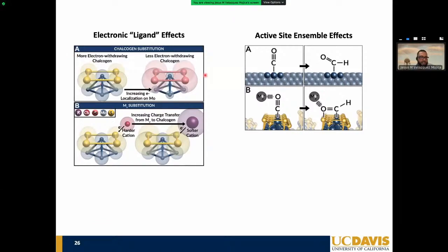I hinted a little bit about the ensemble effect in the previous slide. Here I'm just showing you an idealized cartoon of how the intercalant could perhaps, through electrostatic forces, change that bonding configuration and perhaps impact reaction trajectories from CO2. But also, by changing that chalcogen cage from something highly electron withdrawing to something less electron withdrawing, we could impact the electron localization within the molybdenum. And we know, thanks to some of the theory and experiments done, that the binding site is essentially molybdenum. That is where CO will want to land in this environment.